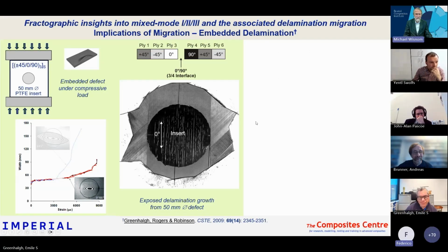Sorry, Emil, I don't quite understand this graph. Is that showing the delamination width in different specimens or in different interfaces of the same specimen? They were the same configuration, the same ±45/0/90 stacking sequence, but different insert positions, different insert depths, yeah. So the 0/90 was between the third and fourth ply, and then the ±45 was between the fifth and sixth ply, but everything else was identical, the defect size, the loading conditions and everything.